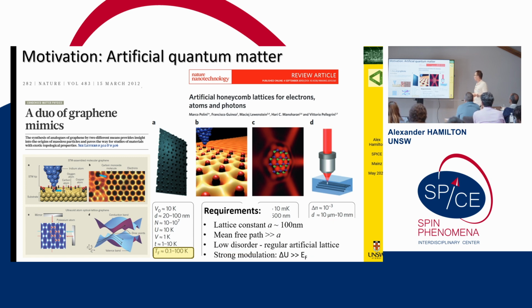If you want to do that, you would want to create synthetic matter with a lattice constant which should be less than 100 nanometers, because that defines your energy scales. Obviously, the mean free path of electrons should be longer than your lattice constant, otherwise it's just disordered. So you need low disorder. You should be able to create a periodic lattice, just like nature does. And you need strong modulation. If you have a very weak modulation, the electrons don't notice there's a lattice. Those are the experimental requirements for making artificial lattices.